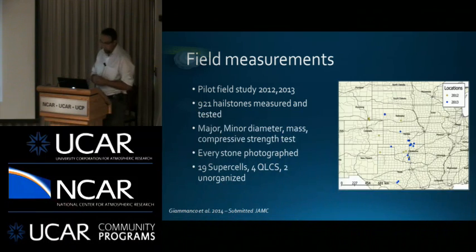So we take a photograph of every stone to actually just see, does it have a layered structure? Is it just that very opaque ice with maybe clear ice surrounding it, and then perform the compressive strength test. So in this 2-year period, you have about 19 supercells in there, 4 linear convective mode cases, and then 2 general, what I would consider unorganized cells. This was based on a radar classification scheme. Our lab is in South Carolina, so we would essentially take a week, fly out to the area, and just go make our hail collection.